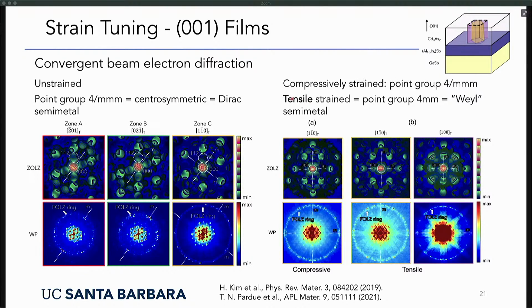The surprise came with a tensile strained film. You can see this. These four diffraction patterns are from the tensile film. These are from the compressive film. You can see in this pattern here, you have these two mirrors. You lose one mirror in the tensile strained film, and what that means is that it has actually lost an inversion center. Okay, and so remember, loss of inversion symmetry normally would get you a Weyl semimetal. In the case of cadmium arsenide, it's a little bit more complicated.